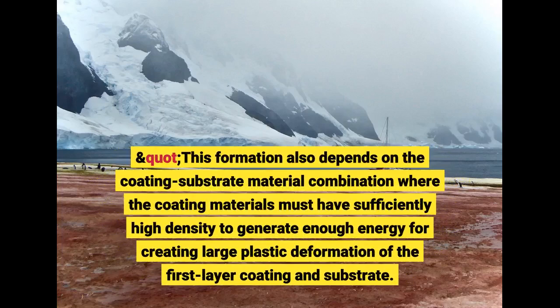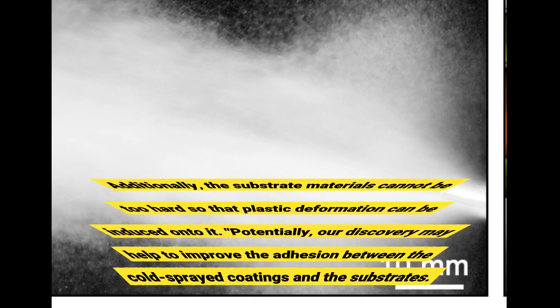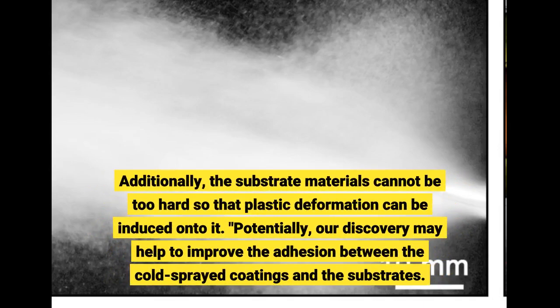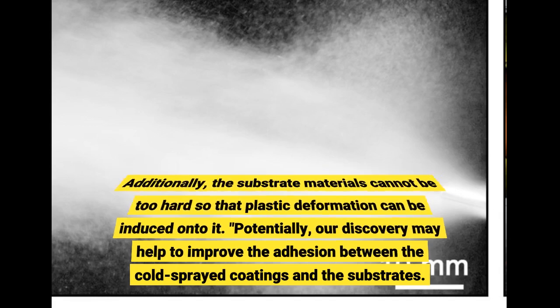This formation also depends on the coating-substrate material combination, where the coating materials must have sufficiently high density to generate enough energy for creating large plastic deformation of the first layer coating and substrate. Additionally, the substrate materials cannot be too hard so that plastic deformation can be induced onto it. Potentially, our discovery may help to improve the adhesion between the cold sprayed coatings and the substrates. To benefit from this, while maintaining reasonable process economy, one could first create an intermixing interface through low DE deposition, followed by production of the coating using optimized processing parameters."